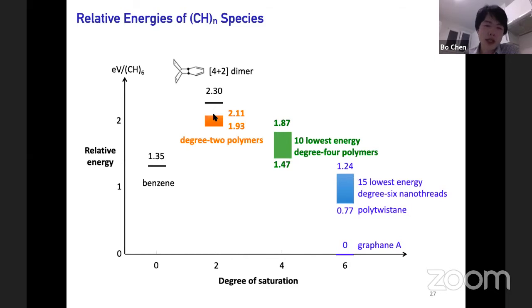So if we focus on the chiral blocks, we can see a clear trend of decreasing energy with increasing degree of saturation. That makes sense because if you go this way, you are converting the relatively weak double bonds, sp2 carbons, into stronger sigma bonds, and then the energy becomes lower, the system becomes more stabilized. But if you follow the trend backwards, you would expect benzene as degree 0 to be somewhere here, but actually it's much lower, here. That's because benzene is aromatic. It has this additional stabilization in it.